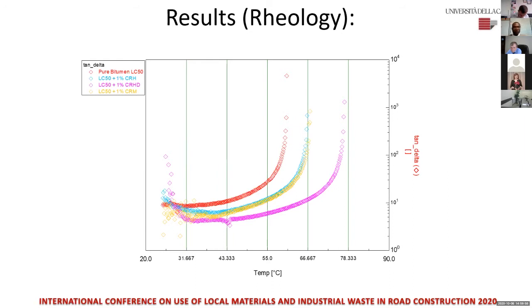As we can see for some of the other analogs, the variants of the same additive, the pink profile gave us the best result, which is about 76 degrees, compared to 60 degrees here. That's about 16 degrees of difference between the modified sample and the pristine pure bitumen sample. So this increases the temperature resistance of the bitumen sample, and it will increase the temperature resistance of the road pavement made with this bitumen with the additive.